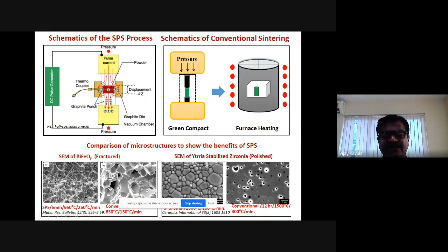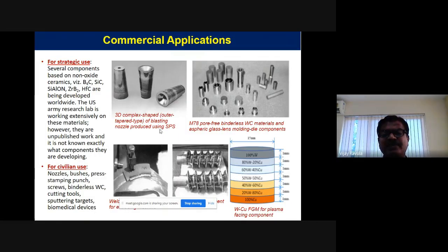Typically, various materials like bismuth iron oxide you can do with very fine grains. Even yttria stabilized zirconia, you can get a very fine grain structure and good density. You can also make commercial 3D complex shaped nozzles. You can produce carbides, zirconium borides, and hafnium carbides, all can be developed using this process. And then you can see the binderless tungsten carbide materials.